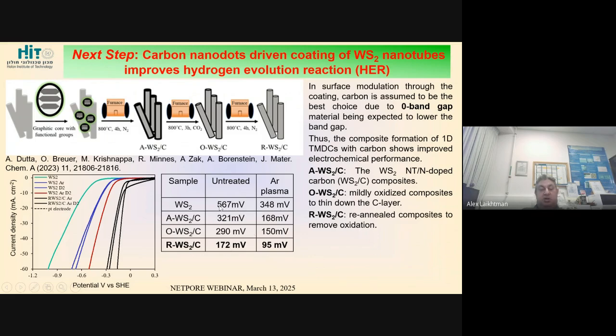So when we have just this carbon coating and no plasma, indeed there is a reduction of the overpotential from 567, which is for untreated nanotubes, to already better than in the case of just plasma, 172 millivolts. But when we perform also argon plasma, and then we also did this with hydrogen plasma and both plasmas, though the results are about the same as just for argon plasma, then we go down even to 95 millivolts. So 95 millivolts is 3 times better than we obtained with just plasma and without this carbon coating. So we are now working on the explanation.